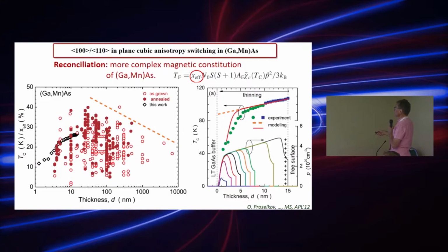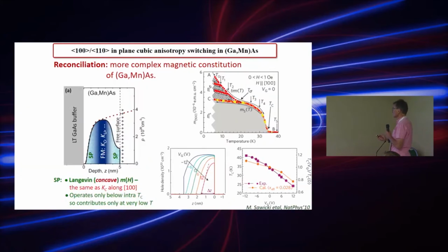So this is the general expression for the Curie temperature in this material, and here stands the spin susceptibility of holes, and that's why with the lowering of the hole concentration, TC goes down. These things are very much related to our studies, since the layers, those which I showed you, are also very thin.